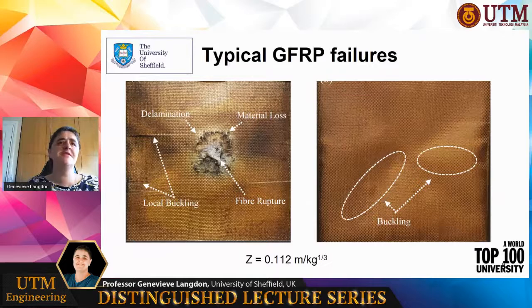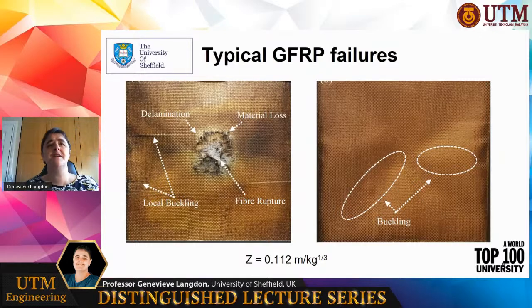This particular material is an S2 glass with a phenolic resin, and it's very thick material. S2 glass is a stronger type of glass fiber than the one you saw on the other screen, which was E-glass. And the dimensions of this panel are slightly larger. In this case, the clamp frame was square rather than circular. And because the material is opaque, you can't see the whitening that comes from delamination. But what you can see on the screen are some of the other typical material failure modes. So this is the same panel. The image on the left is showing you the loaded side, and the image on the right is showing you the rear side.